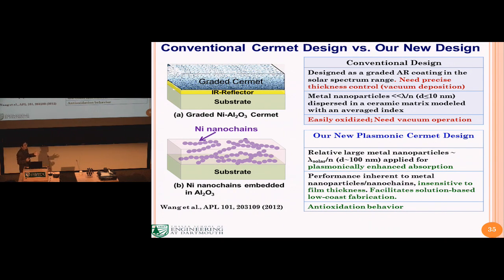The reason why the metal nanochains were reflecting light is because there's a refractive index difference between air and metal. If you bridge that gap gradually using a graded layer where you increase the volume fraction of metal nanoparticles from top to bottom, you can reduce the reflectance in the solar regime. Because the substrate is usually a metal, the light is not going to be transmitted through. So if you have low reflectance in the solar spectrum regime, that means you have high absorptance in this material in the solar regime.